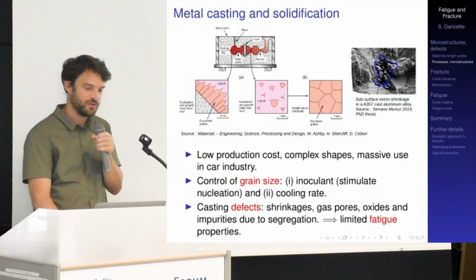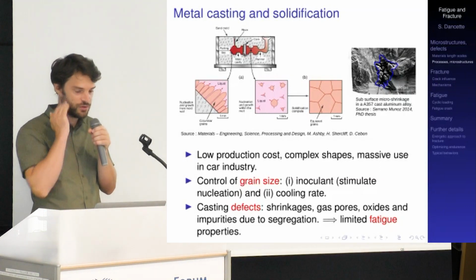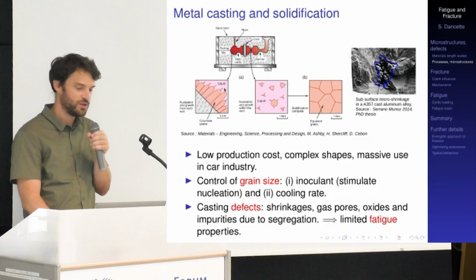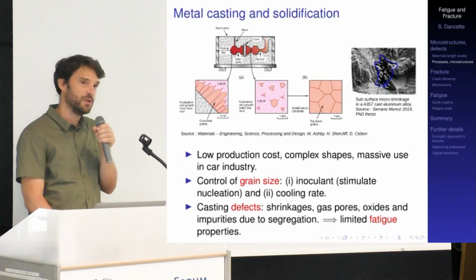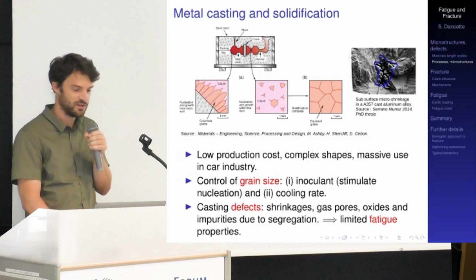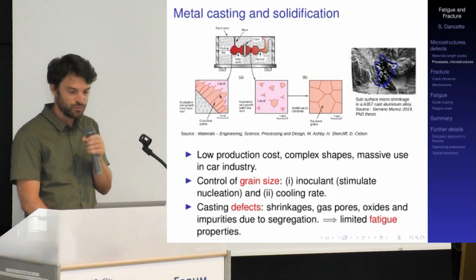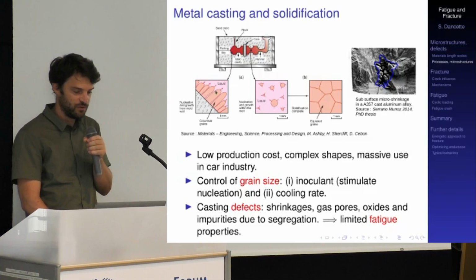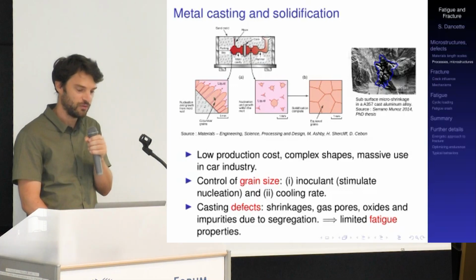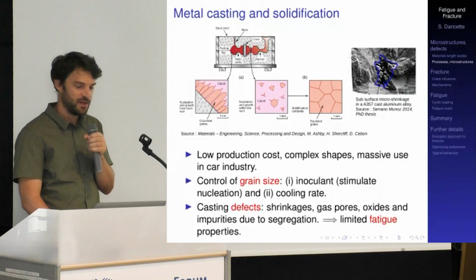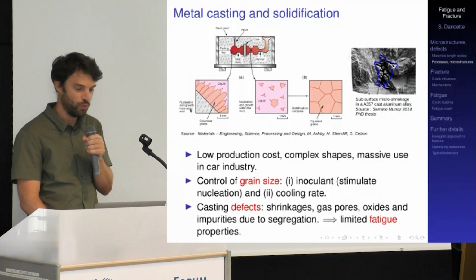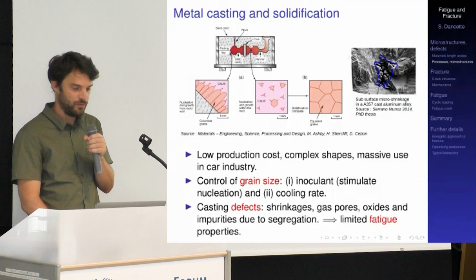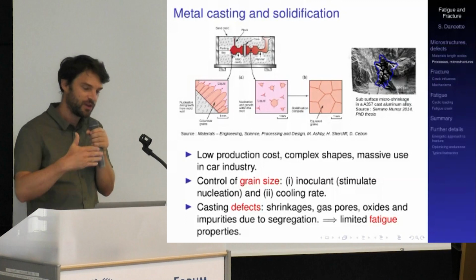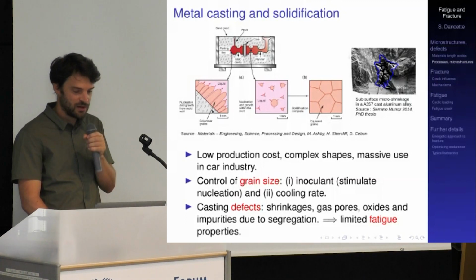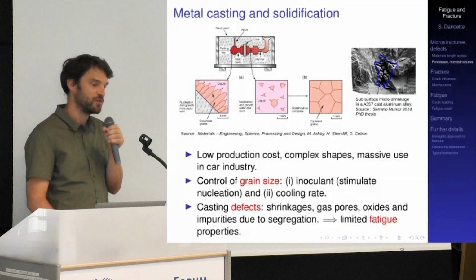So the problem with this, obviously, is that you have a liquid that will have to undergo solidification. And when you start to think about solidification, it implies a lot of metallurgical transformations and metallurgical phenomena, starting, as illustrated here, from the way the very germs of solid are going to initiate from the liquid. And you can see in this illustration that the way the grains are going to grow from the liquid will be different if this happens on the mold wall, for example, on the very exterior of the mold, with a direct contact with the sand mold in this case. In which case you will most likely have such columnar grains here that will occur during solidification.